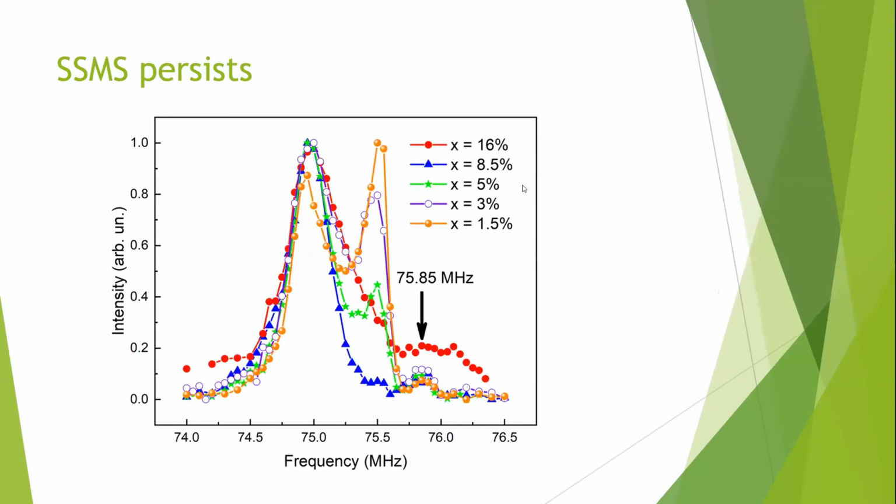Then we can see all the spectra in one. And what can we see here? This left wall, maybe it's speculation, but I see it this way. This left wall is the same for all the spectra. For example, if we expected destruction of the spatial spin modulated structure, we would have seen symmetrical destruction, so some symmetrical line. It would be broadened there and there.